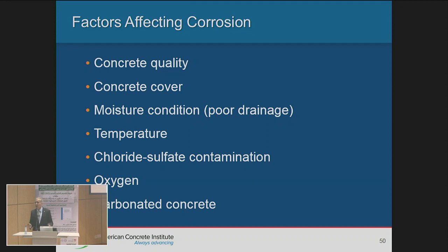So, why does steel corrode? There are different factors that affect its failure. For example, first of all, the concrete quality. Do we have good quality concrete? The water cementitious ratio. Do we have chloride in the mix? I'm sure that nobody here would allow any chloride additions, like admixtures that have chloride content, to be included in the mix design. The concrete cover. Do we have adequate concrete cover? Many times we find that concrete cover is not there. Temperature, chloride, sulfate, oxygen. All those will affect whether we get corrosion or not.